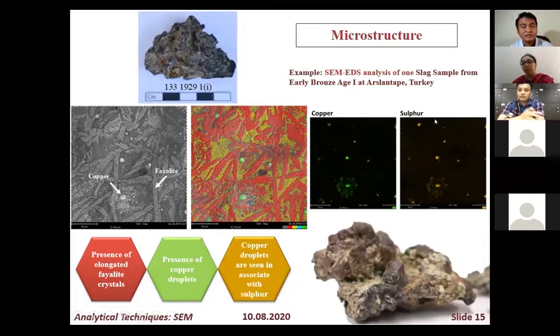And most importantly, we also know where the sulfur is. If we overlap this elemental map, we can easily see that sulfur and copper are associated in the same position. This means copper is associated with sulfur. It indicates that maybe this slag is a result of being extracted from a sulfur-based ore.